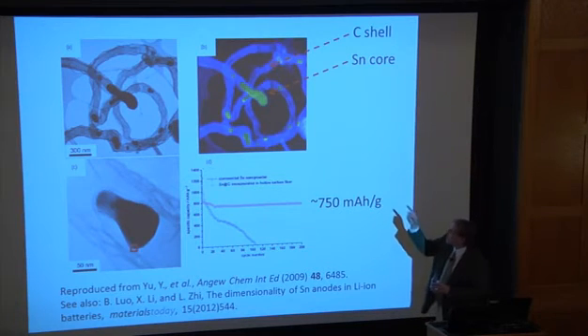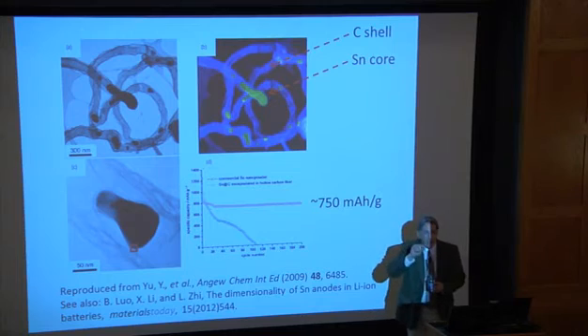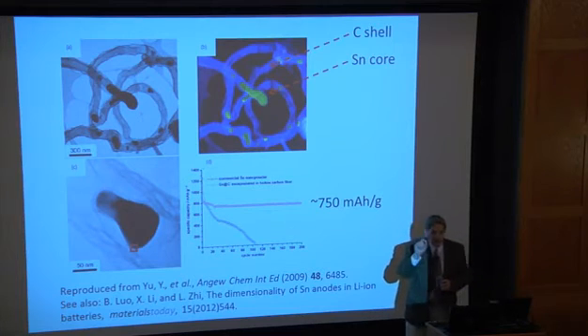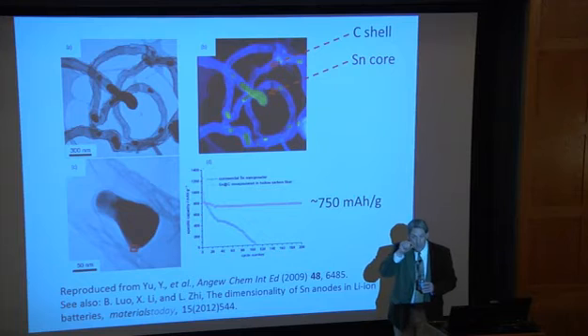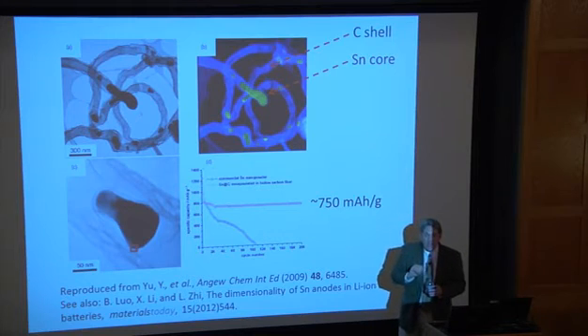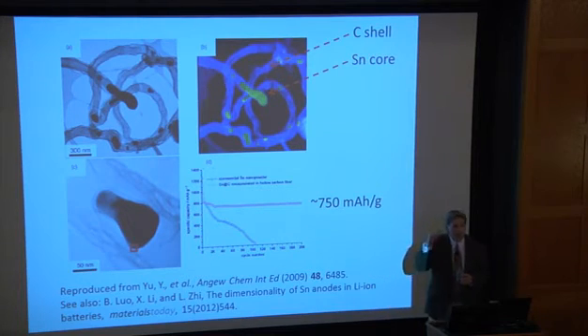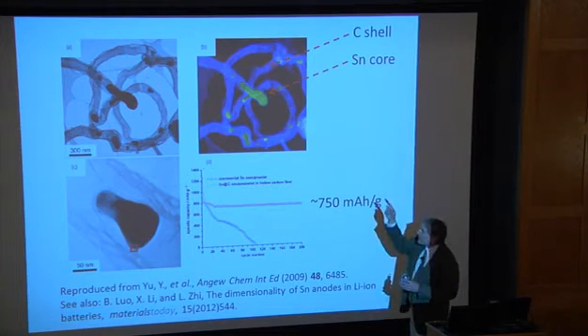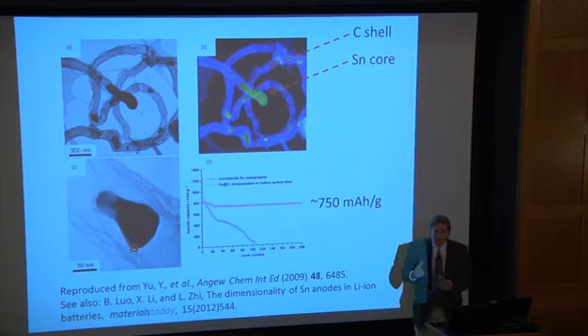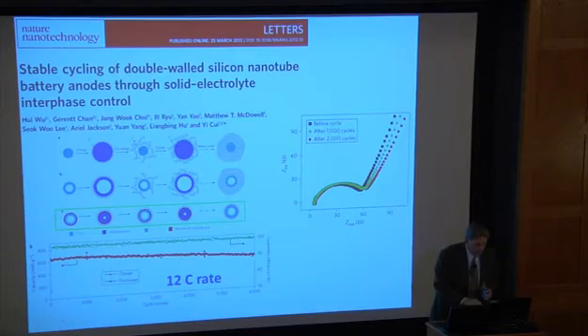And the notion, as you can see, is that you have an outer carbon shell. Now, we know carbon passivates by an SEI layer, so it adds this terminating passivation layer to the tin that protects it from further degradation with the solvent. And then inside, the active material is the tin, and it's protected then from the electrolyte reactions.